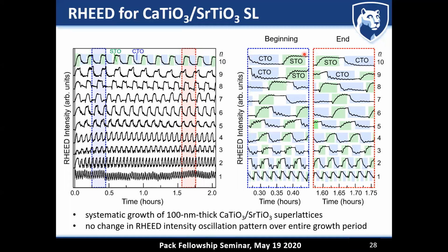And so the exciting part is that this layer by layer control we've achieved for all of these superlattices, irrespective of how many layers we had per strontium titanate or calcium titanate. But then the other exciting thing is that you can see that the intensity oscillation and the trends really look the same at the beginning of the growth and also at the end of the growth, which gives you an idea of how stable this hybrid molecular beam epitaxy approach is.